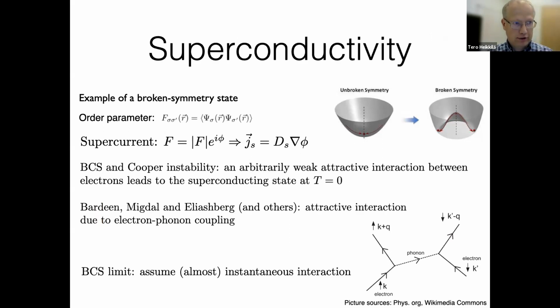Okay, so how do you get to this finite order parameter? Basically, what BCS, Bardeen-Cooper-Schrieffer, and especially Cooper, showed is this Cooper instability: if you have an arbitrarily weak attractive interaction between electrons, this leads to a superconducting state at zero temperature. Then Bardeen, Migdal, Eliashberg and others showed how this attractive interaction arises from electron-phonon coupling, at least. There are also other mechanisms, but this is the best known one. At least for conventional superconductivity, this is the relevant mechanism. Also, in the BCS limit, one usually assumes that this interaction, even though it's mediated by phonons, is almost instantaneous.